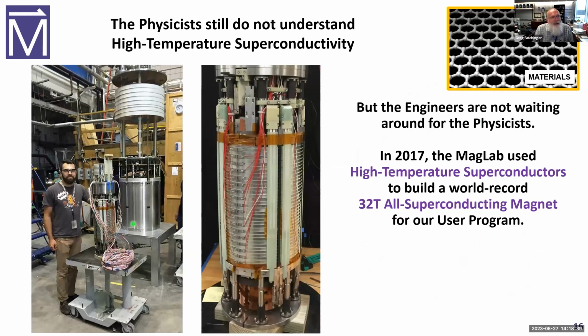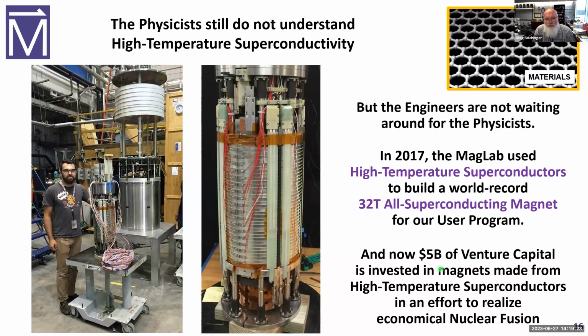Well, the physicists still don't understand high temperature superconductivity, but the engineers are not waiting around for the physicists. And so in 2017, the MagLab used high temperature superconductors to build a world record 32 Tesla all superconducting magnet for our user program. This is the high temperature superconducting inner coil that was then inserted inside this outer coil made of conventional superconductors for this total 32 Tesla magnetic field. And this photo here on the right is just an enlargement of that high TC coil. And at least partially because of the success at the Magnet Lab, there's now $5 billion of venture capital that's invested in magnets made from high temperature superconductors in an effort to realize economical nuclear fusion.